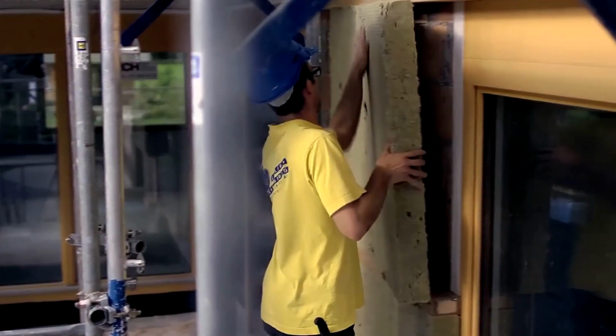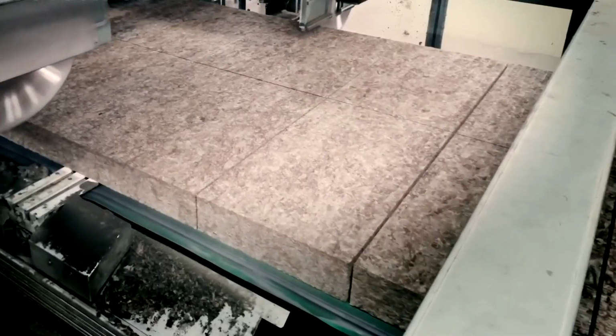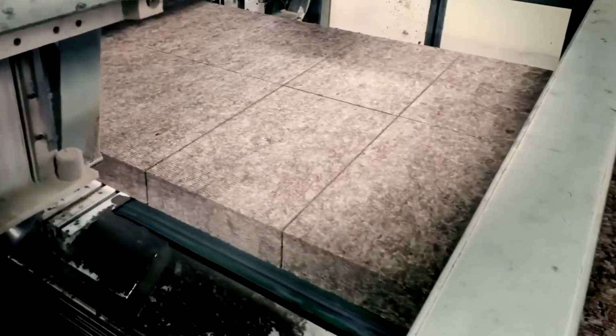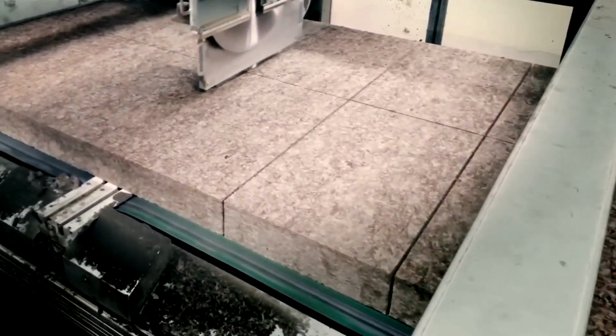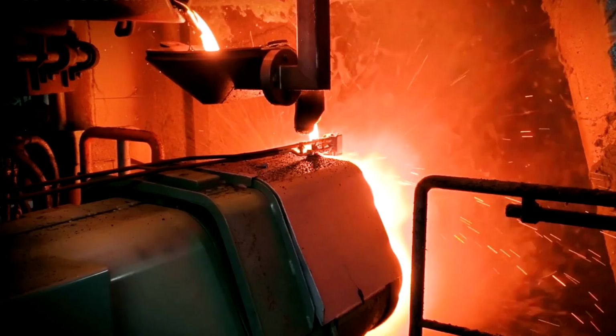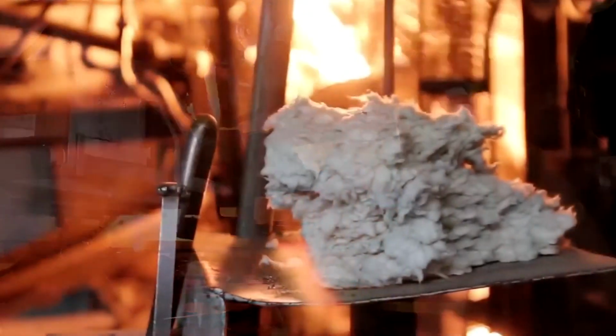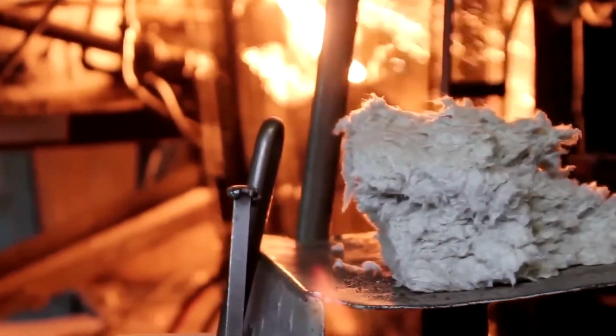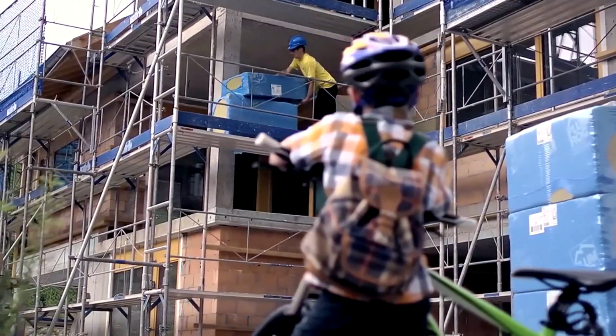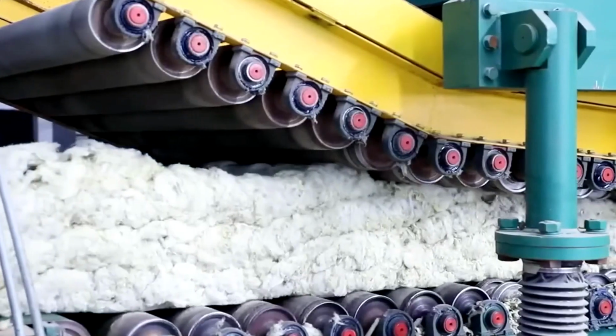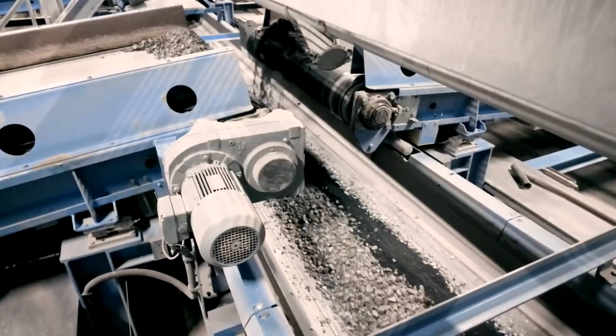The Rockwool slabs are now formed, but they must first pass a series of crucial quality tests. Part of this inspection involves checking their hardness, where pressure tests ensure the slabs can withstand mechanical stress without losing their shape or density. And because mineral wool is valued for both its insulating and fireproof qualities, a fire test is essential. A flamethrower blasts the surface, raising temperatures to around 1,200 degrees Celsius. In a striking demonstration of its power, a person can sit directly behind the slab, comfortably reading a newspaper, completely shielded from the intense heat.